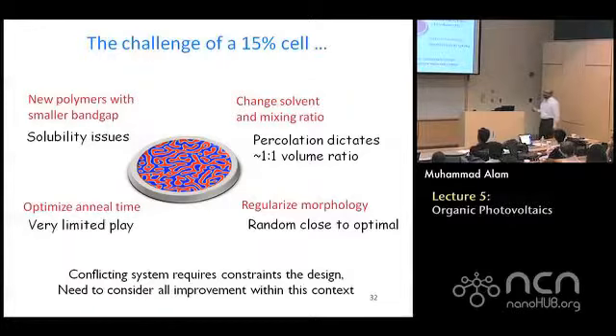Some people might say, why not change the ratio of the blue and the red? 1:1 is good, but maybe the red one, if it absorbs all the light, generates all the excitons, then maybe I should make it 3:1 so that I can catch a lot of light and a lot of excitons, and that will be good. But it turns out that the percolation theory suggests that you cannot go too far beyond 1:1. It doesn't really matter what you do, it's a geometry problem. And physics you can beat, geometry is very difficult to beat. You can say, yeah, we'll optimize anneal time, not very much you can do. And then you can do regularized morphology, but as I said, random maybe in some cases close to optimal. So you're in a tight box.